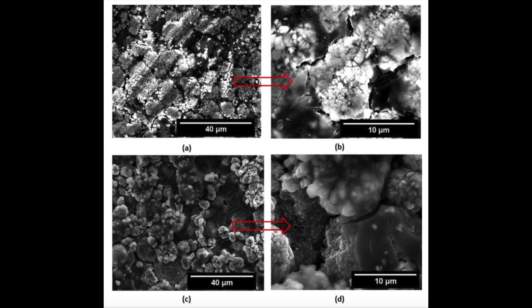Another interesting aspect of this study is the scanning electron microscope images, or SEM images, which show the difference in crack propagation after cycling in the wet versus dry. The authors comment that for the dry electrode in A and B, the cracks appear at the NMC grain boundaries, but for the wet electrode, the cracks appear to be throughout both the NMC particles and in the carbon black and binder. You can see the dry images up top and wet images appear different altogether, and it may have been that slightly different contrast and brightness settings were used to focus on each, one of the inherent challenges of using SEM to characterize materials.